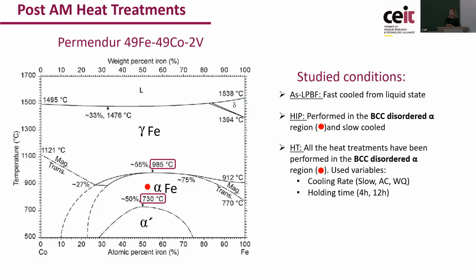after conventional heat treatment. About the heat treatment, what I have to say is that all the heat treatments were done in this region, in the disorder alpha iron region, and then the differences were the different cooling rates and the different holding times.